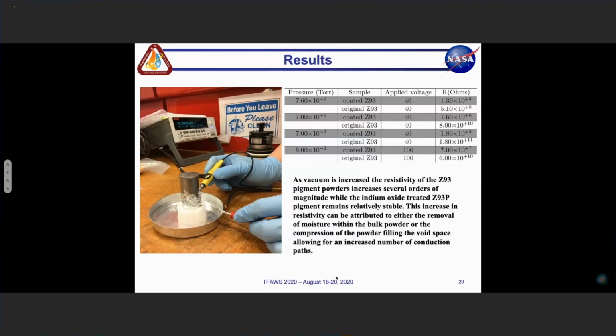So we were able to take these pigments, both your coated pigments and your uncoated pigments, put them through a compression process and put them in vacuum to measure the resistivity across these pigments. And what was interesting to note is that as we increased our vacuum, the resistivity increased by 3 orders of magnitude once we reached 10 to the minus 2 Torr. And the